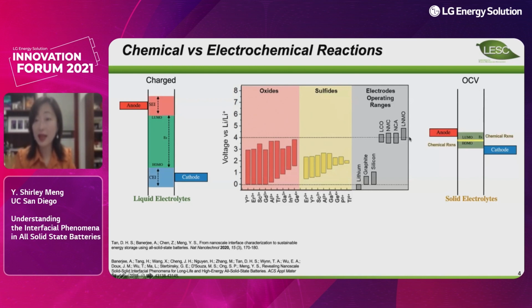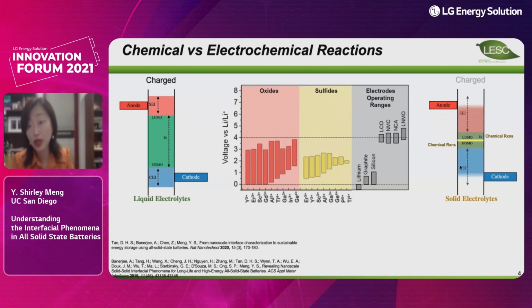So what happens is that the chemical reactions first need to be stopped. And that's one of the reasons the road for solid-state batteries is very difficult, because many people pick oxides as the first solid electrolyte priority to study. But sulfides indeed took quite a long time, because not only do we have to deal with chemical stability, when you start to sweep the voltage, the electrochemical stability will also change. So this becomes a double jeopardy for our solid-state battery development.